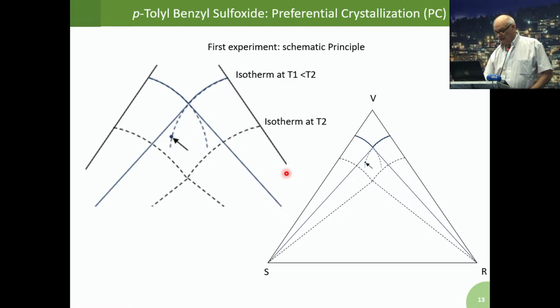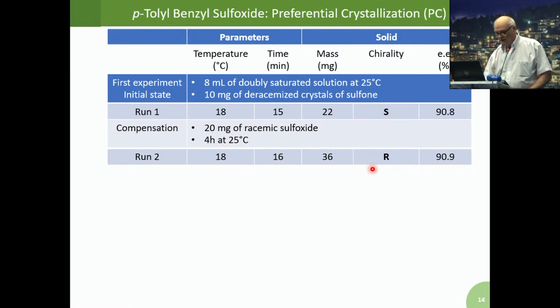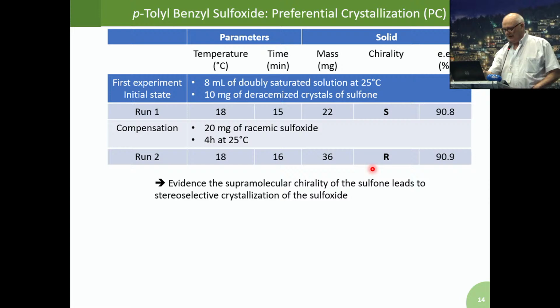And then we perform the preferential crystallization, which means what? We have here two isotherms, which are extracted from this figure here. So starting from the racemic composition, which is pointed here, we go to the high temperature, T2, and then we dissolve everything. Then we cool this solution down to T1, where we have first a supersaturated solution, and then we seeded this supersaturated solution with the sulfone, which has been deracemized. And then you can see what we obtain. Okay, so at 18 degrees, by letting 15 minutes, and by seeding with the deracemized sulfone, we obtain the S enantiomer with a quite good 91% of enantiomeric excess.